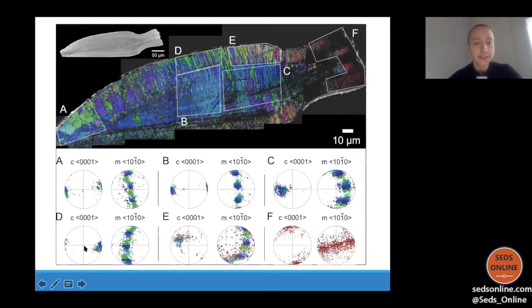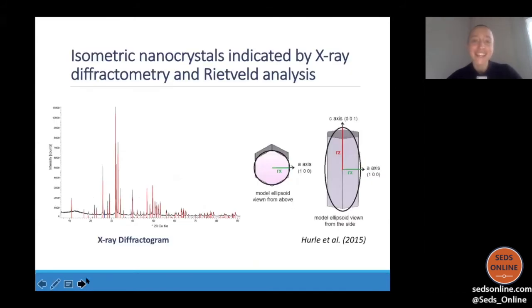So you can see, again, looking at the C-axis, it is perpendicular to the surface of the sample, which you will remember is different from what we've seen, for example, in aragonite. And it has implications for the material properties of the mineral. And the A-axes are, again, forming a girdle structure, which means that the crystals rotate around the C-axis. The surface is quite well ordered, but if you look into the inside and to the tip of the specimen, the crystals grow very big and they seem kind of fused. And I think Chelsea will know, she will have seen this before, but in carbonates.